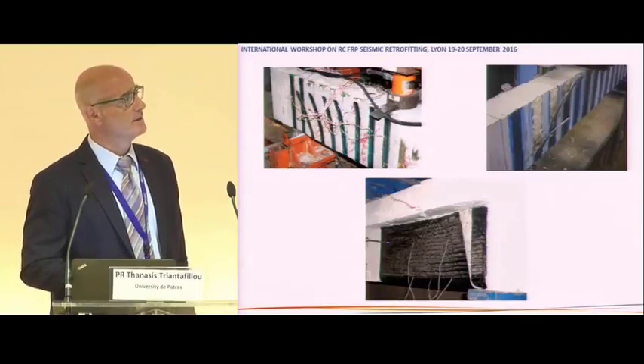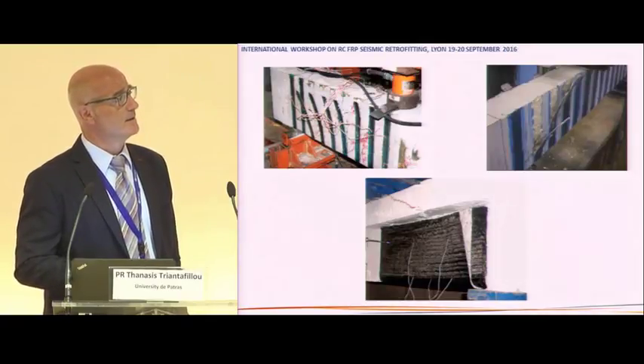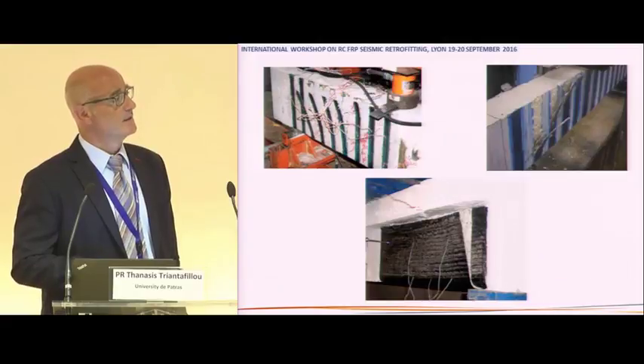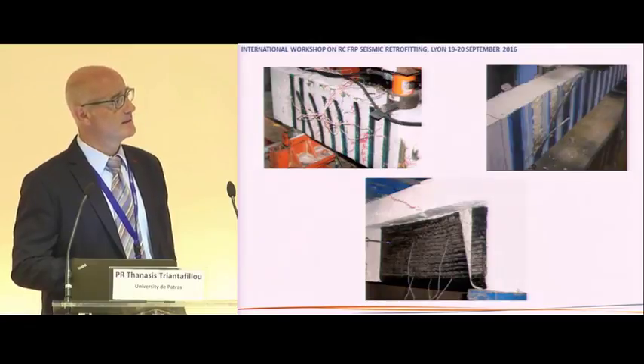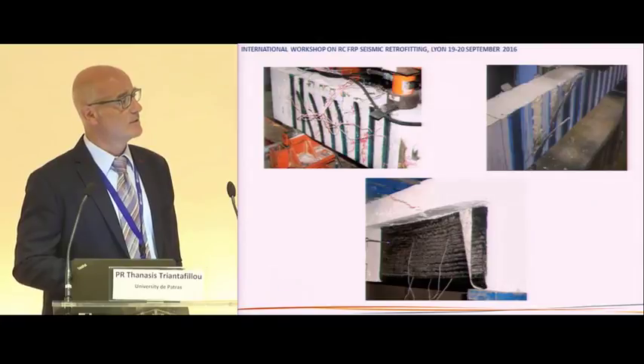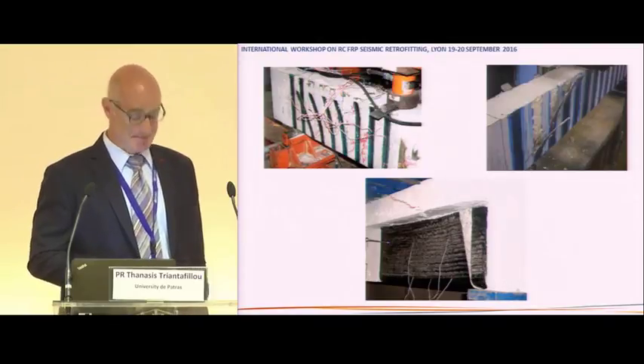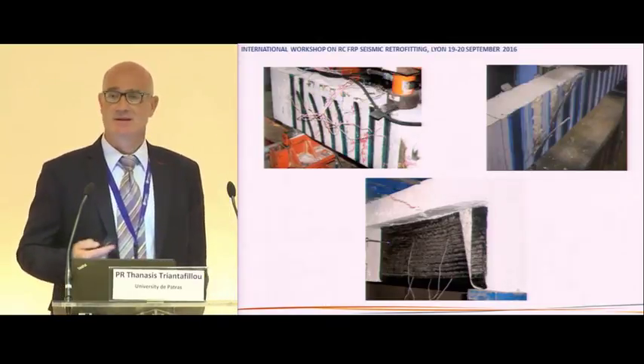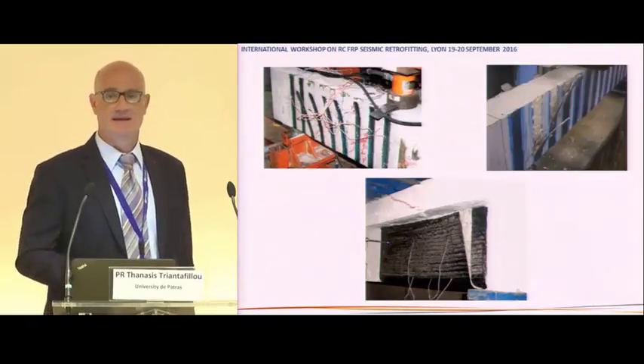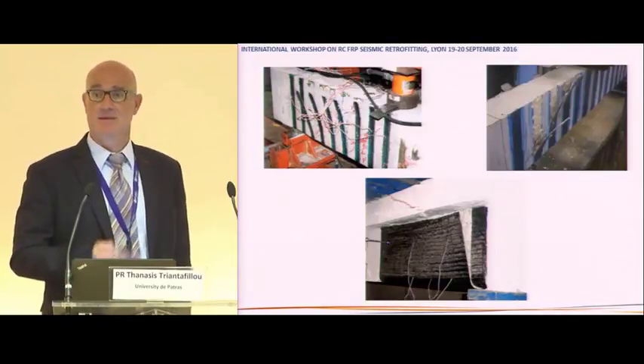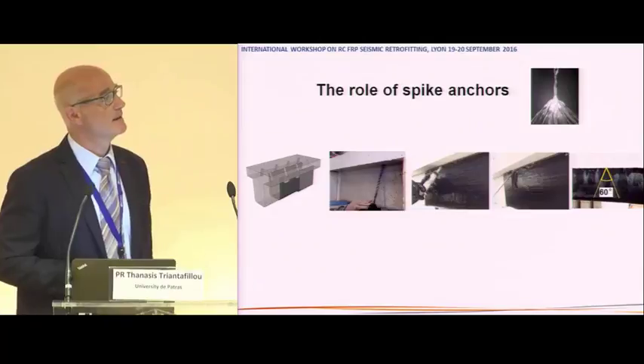Speaking about debonding, you see what I mean here. This is an open jacket. These are strips applied to do shear strengthening. The fibers are not continuous, so most likely what we expect is this type of debonding in the free part, which is also shown here. So the fibers are not utilized to their full capacity, and that is something to be taken into account in design.